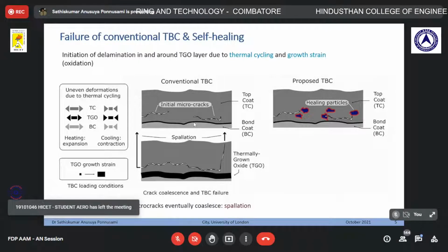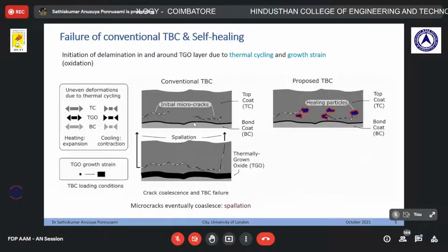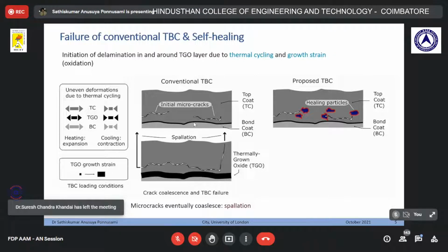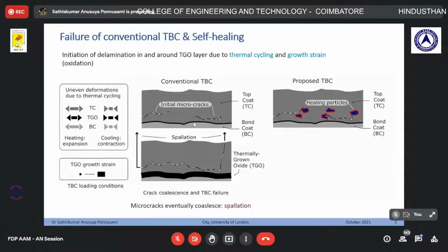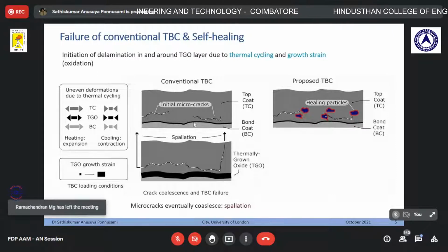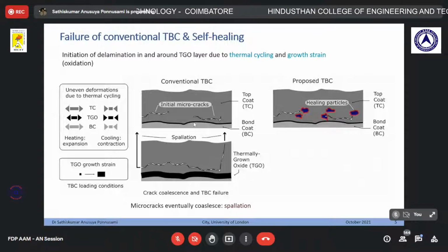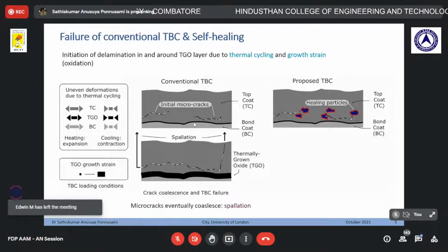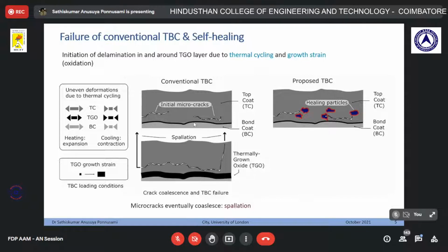Yeah, and what these healing particles do is this: when micro cracks happen, meaning when the flight is in operation and then lands, thermal stresses lead to cracks. When these cracks interact with the healing particles, the cracks open the particle. Once it opens, the particle contains a specific healing agent, and that healing agent diffuses through the crack. And through further oxidation, it heals the crack, thereby regaining the structural integrity.